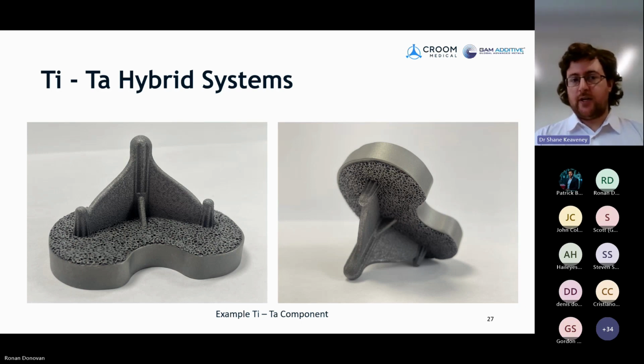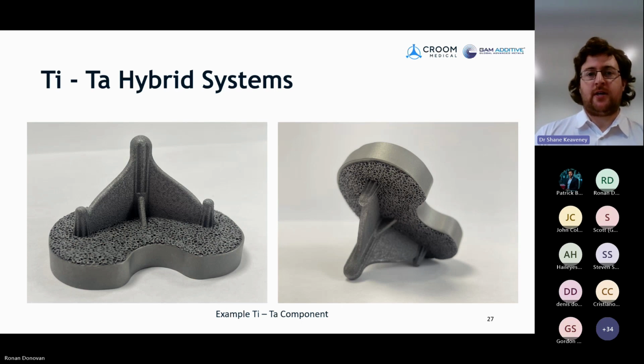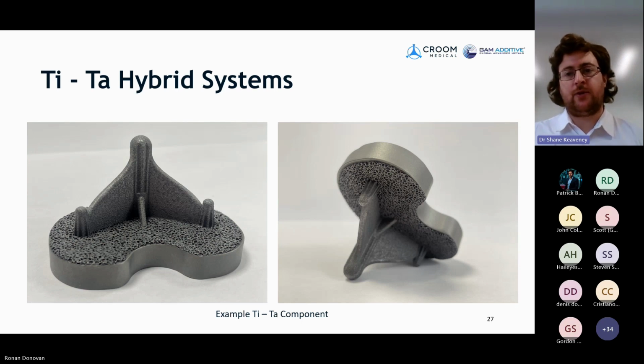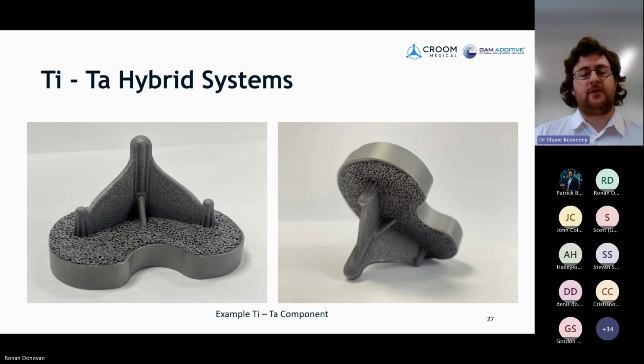Now this is quite nice because with the powder bed fusion process, we can obviously just go from like onto a flat surface. But potentially that could be expanded. But here we've just done like a flat substrate, tantalum printed on top, and it works quite well. We are currently working a little bit more to understand the interface between these two materials and how to improve it. But at the moment, the results are very promising, so it seems like a good option.